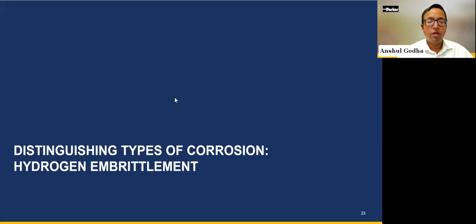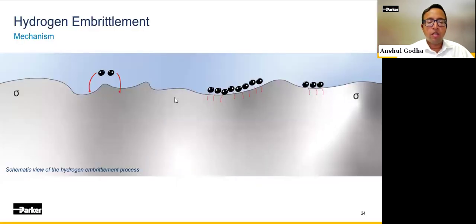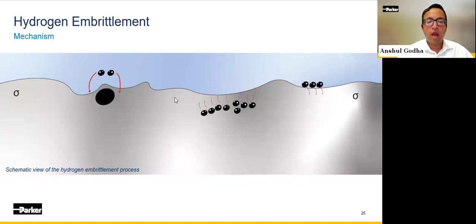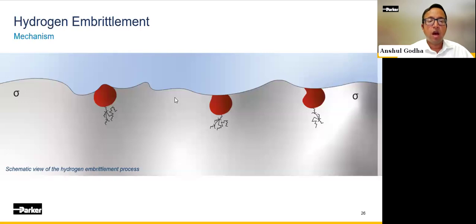Next, let's talk about hydrogen embrittlement. The basic mechanism of hydrogen embrittlement is where you have individual hydrogen atoms that are created close to the surface of the alloy. Because of their really small size, they fairly easily diffuse into the metal. Once they have diffused in, they can either just come back out, in which case no harm done. However, in some cases, these atoms can actually combine to form hydrogen molecules inside the metal. This hydrogen molecule is much bigger in size than the individual atoms, and therefore applies a ton of stress in the metal right around the molecule. Eventually, this stress leads to the cracking.